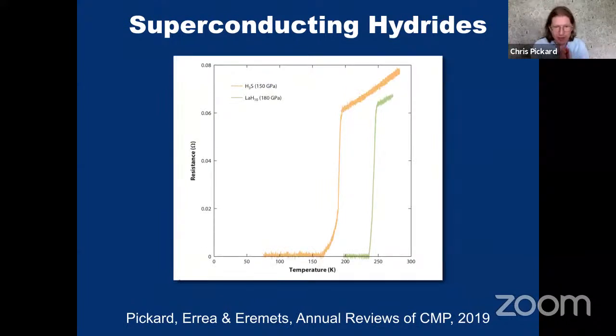So here's some very clean experimental data from Mikhail Eremets of the transition for hydrogen sulfide, H3S, and lanthanum hydride, LaH10, at higher pressures. So we're getting towards the 150, 200 GPa. There are some debates in the literature as to whether this is really superconductivity or not. My impression, talking to several different experimental groups measuring these transitions, is that something's happening here. It looks rather like